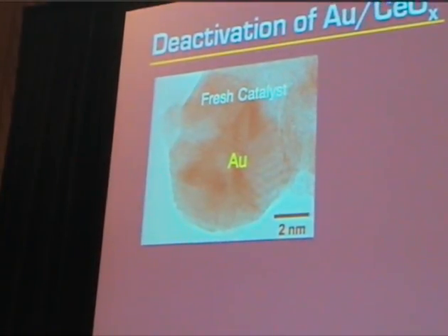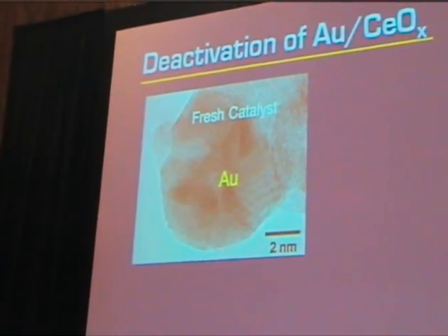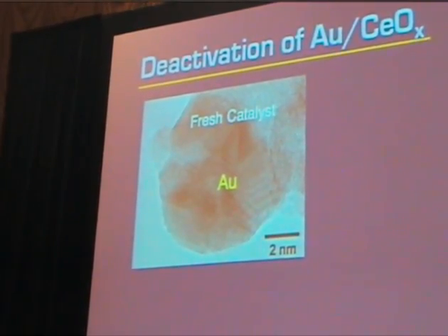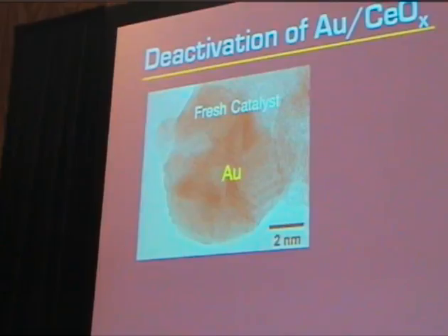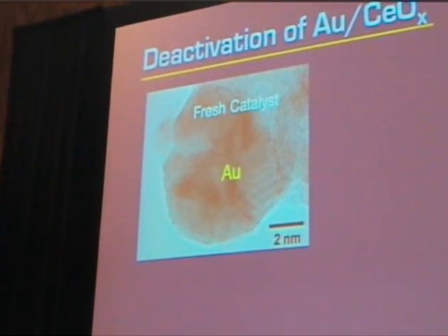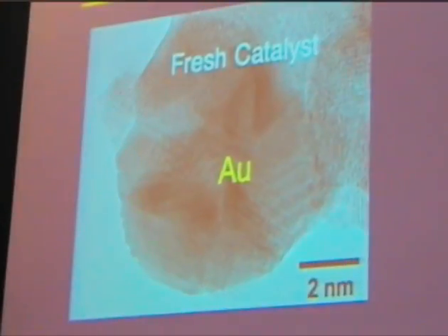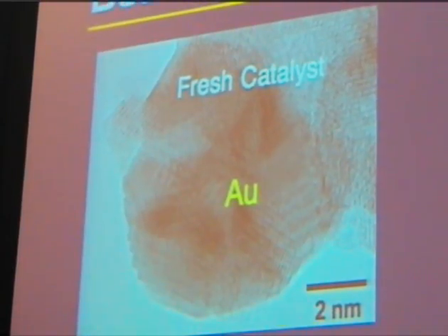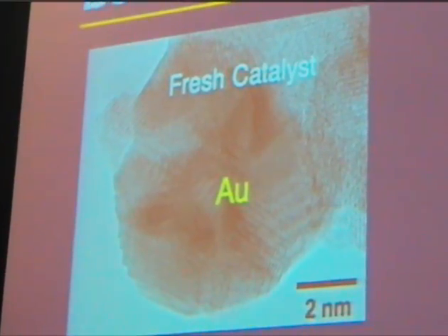Unfortunately, we don't have an in situ transmission electron microscope available at our institution. So what we did was take out the sample grid, put it in the water gas shift reaction stream and soak it for about 4 to 12 hours, then put the grid back in the TEM instrument and try to find the same particles in what we believe is the same region.